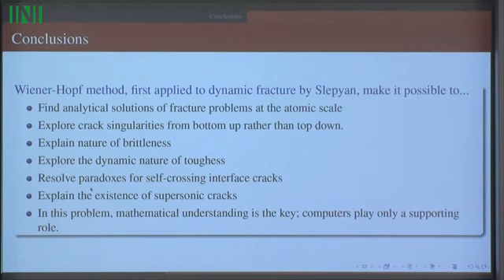So here's what you can do with the Wiener-Hopf methods in these particular cases. You can solve at the atomic scale dynamic fracture problems as unlikely as that may seem. So that means you can explore crack singularities from the bottom up rather than from the top down. I claim that lets you understand the very nature of brittleness, the tendency to move along certain planes and the tendency to be fast. You can find the dynamic nature of toughness, why it costs more to move a crack faster. You can calculate it.